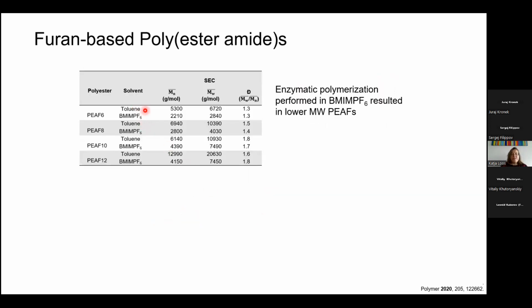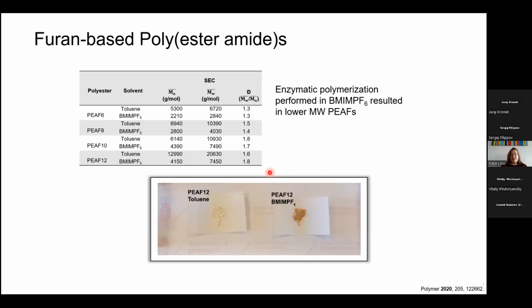But the different solvents, and so this is one of the first approaches where we went to ionic liquids and green solvents, because it's difficult to work in bulk, and toluene you of course want to avoid. We still get lower molecular weights. We also started to work with deep eutectic solvents, and then the story is again different. I don't have results on that, but we also see that, for instance, with the ionic liquids, we get discoloration, which is of course not nice. So this is not the discoloration of the monomer, but this really stays in there from the ionic liquid. So this is interesting, and I think we should move more and more into these green solvents.